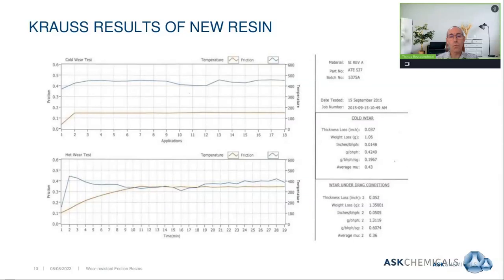Let's move on to the wear behavior. And now we see on the right here a number of 0.19 at low temperature. If you compare that to the number of 0.32, now you sit at about 60% of the original wear compared to the old technology. But then look at the behavior of wear at high temperature, 350 degrees Celsius. You have a number of 0.6 compared to the previous number of 1.79, which is about a third of the wear of the older technology. So a substantial improvement in wear resistance.